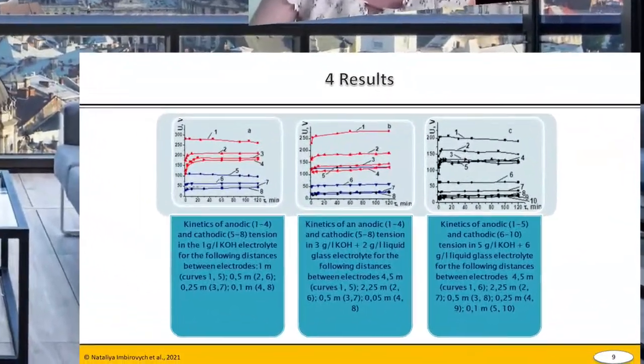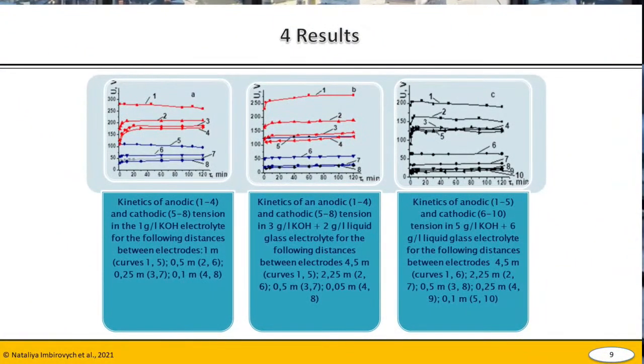So, as you can see from poster 9, the plasma electrolytic oxidation process takes place in the anode and cathode modes. The corresponding voltages, measured by voltmeters, are stabilized in a few minutes. The initial rapid increase in such voltages is due to the breakdown of the conductive film on the metal. Depending on the composition of the electrolyte and the distance between the electrodes in the synthesis of coatings, the voltage values of the anode, VA, and the cathode, VC, were verified. After the breakdown phase of the oxide film, the synthesis process proceeds evenly, as evidenced by the slight change in voltage at the anode over time, which is characteristic of the electrolytes.